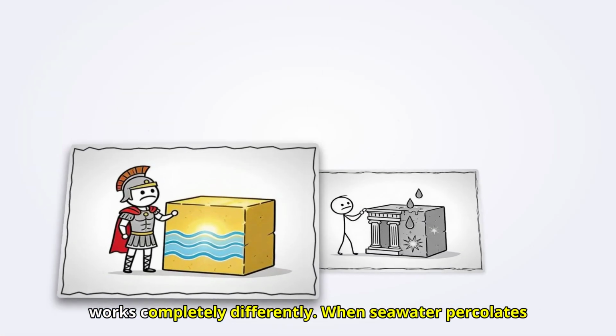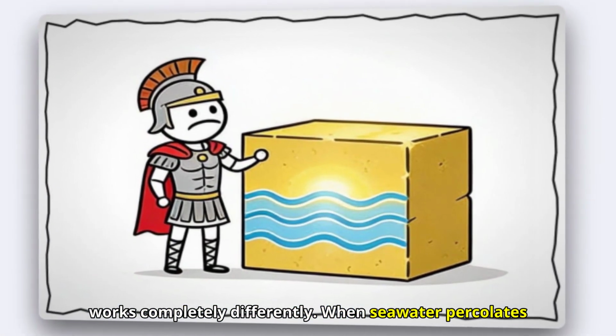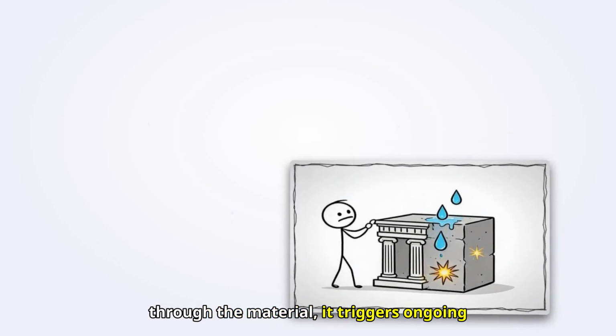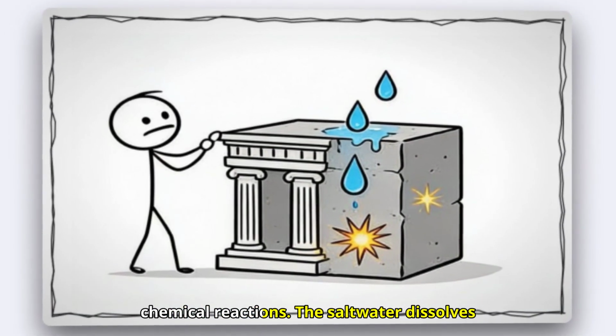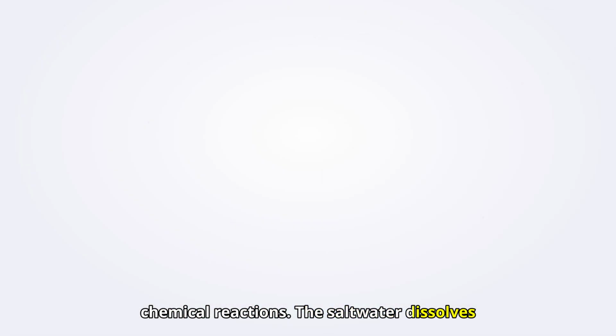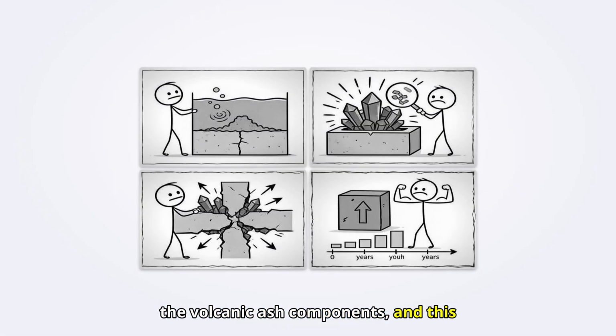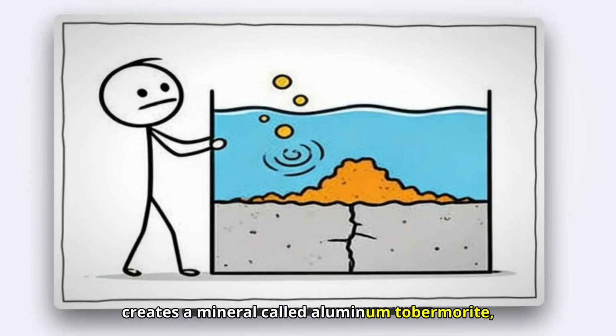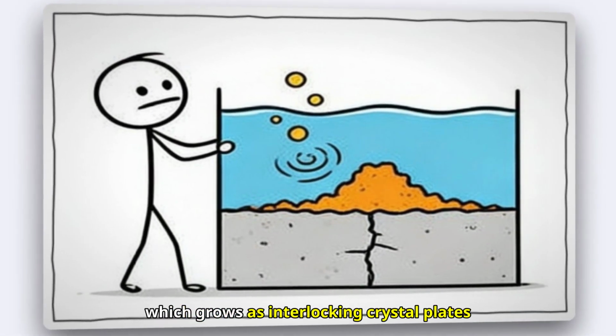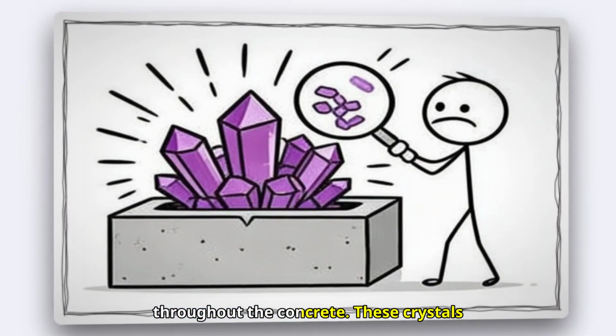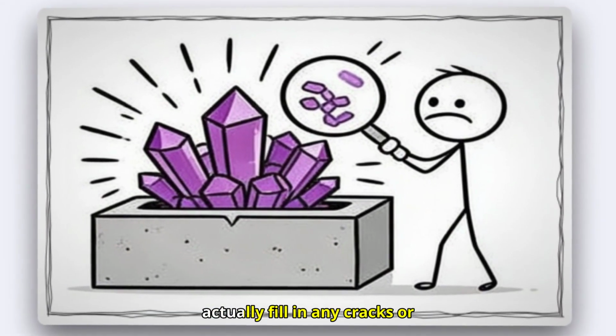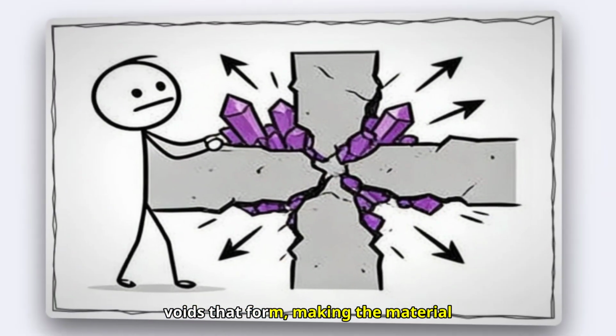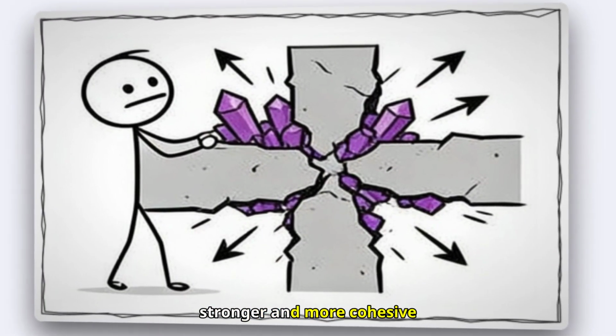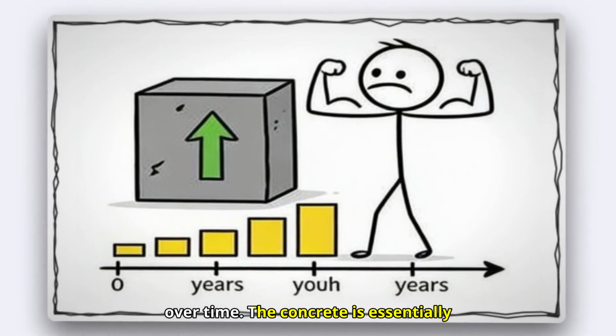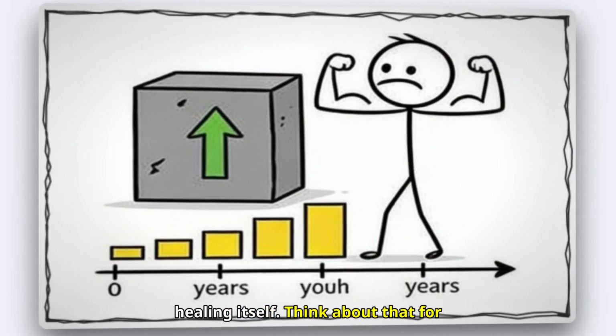Roman concrete works completely differently. When seawater percolates through the material, it triggers ongoing chemical reactions. The salt water dissolves the volcanic ash components, and this creates a mineral called aluminous tobermorite, which grows as interlocking crystal plates throughout the concrete. These crystals actually fill in any cracks or voids that form, making the material stronger and more cohesive over time. The concrete is essentially healing itself.